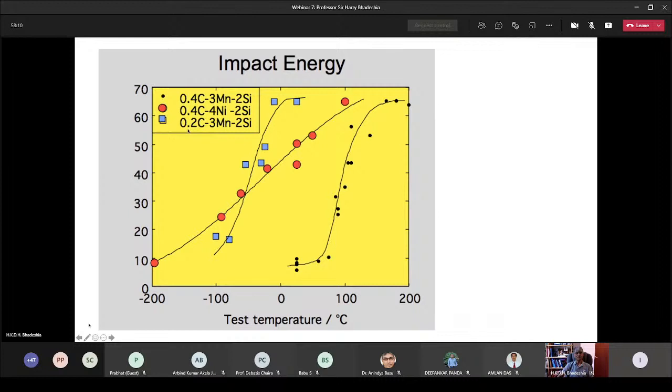And this is the X bar being reduced from 0.4 to 0.2. Very simple calculation. You have dramatically improved the toughness of the steel. And the strength, I emphasize, is not compromised. In other words, we get the same strength in all three, about 1600 megapascals, without compromising the toughness. So what I want to emphasize is that going from the mechanism of transformation, understanding from an optical micrograph that you have large islands of austenite which will decompose to martensite under stress and therefore make your material brittle, and then using the simple T0 analysis without doing any experiments, we predict two alloys which should behave much better, and they do in practice.